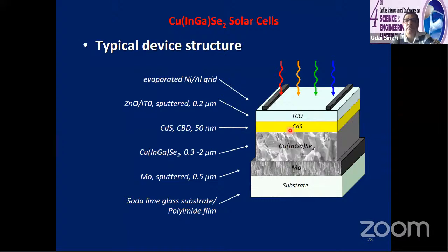Then you have a cadmium sulfide, which is a thin layer of 50 nanometer. And then you have a transparent conducting oxide because the light is coming in this way. So it's basically a bilayer. We have a certain intrinsic layer of zinc oxide, which tries to avoid any shunting path. And then you have the aluminum-doped zinc oxide or the ITO, which is the transparent conducting oxide.